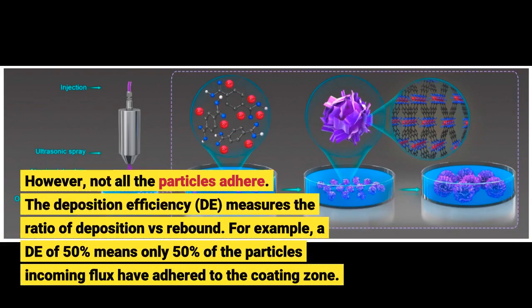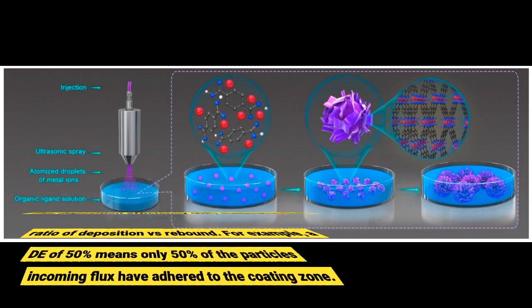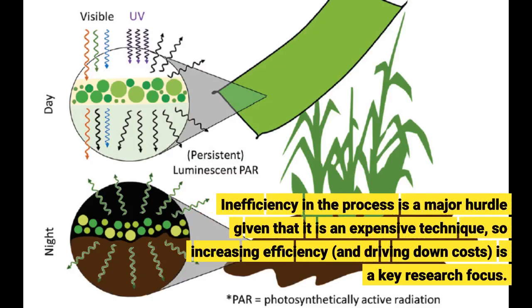However, not all the particles adhere. The deposition efficiency (DE) measures the ratio of deposition versus rebound. For example, a DE of 50% means only 50% of the particles' incoming flux have adhered to the coating zone. Inefficiency in the process is a major hurdle given that it is an expensive technique, so increasing efficiency and driving down costs is a key research focus.